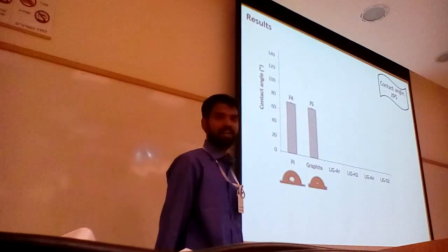We found that these two hydrophobic samples have lesser quantities of oxygen, and LIG that is fabricated in oxygen atmosphere is extremely hydrophilic because it has about 9% oxygen. Even though LIG air is hydrophobic, it contains a higher degree of oxygen when compared to these two samples. Why?